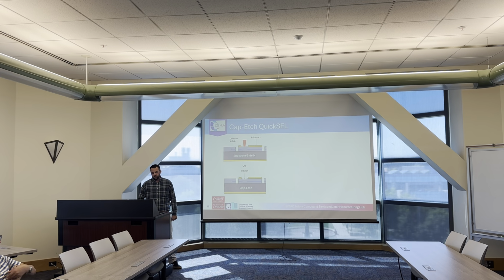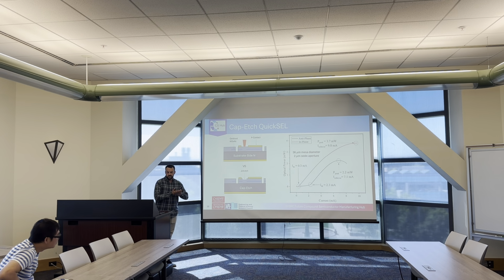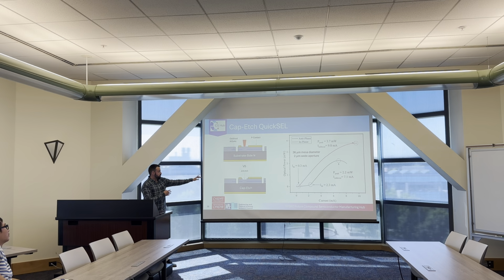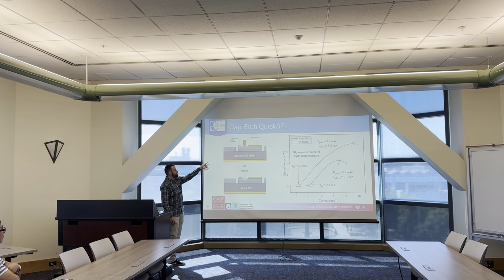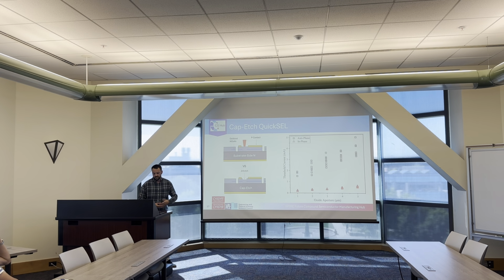So we qualified that as well. These are performed on the same wafer, devices in close proximity, as grown versus quarter wavelength etch. So the black curve is the as grown, and after a quarter wavelength etch you see a huge reduction in the threshold current, which is even more obvious when we look at it as a function of oxide aperture for a large amount of devices.